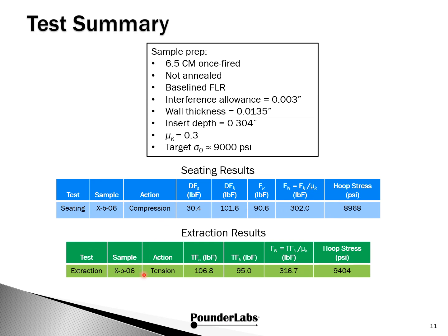On extraction, the action is now under tension. TFS is up at 107. The TFK at 95, and we calculate a normal force using tension force kinetic instead of the insert force kinetic. We get 317 pounds of force, which gives us a hoop stress of about 9,500, just a scooch above what we expected. So we find it really fascinating that this process is virtually reversible and provides a lot of insight to what's going on with bullet seating.